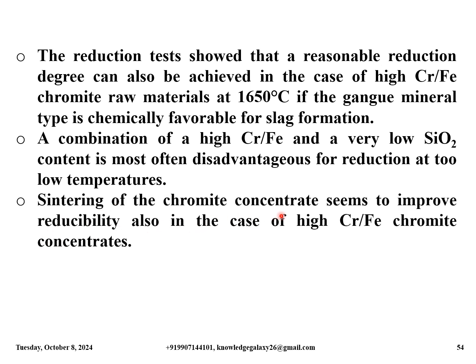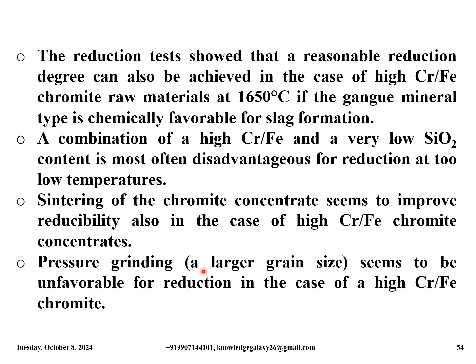Sintering of the chromite concentrate seems to improve reducibility also in the case of high Cr/Fe ratio chromite concentrates. Pressure grinding, that is a larger grain size, seems to be unfavorable for reduction in the case of a high Cr/Fe chromite.